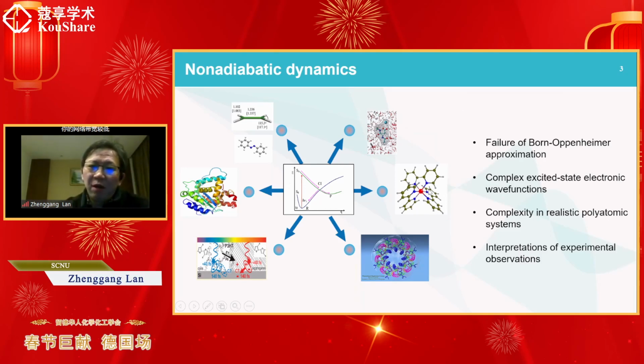So for the OLED materials, sometimes you have to use a transition metal complex. For this transition metal complex, their photochemistry also involves the surface crossing, for example, from the singlet to triplet, and also the non-adiabatic transition. And also, if we go to photobiology, sometimes we have a lot of photostability and photo-induced energy transfer. This process is also covered by the non-adiabatic transition at the surface crossing area.